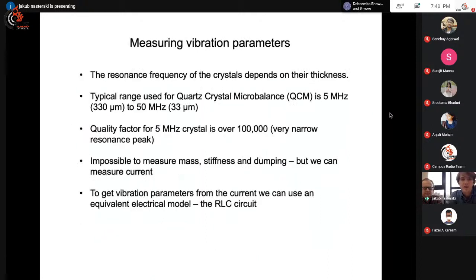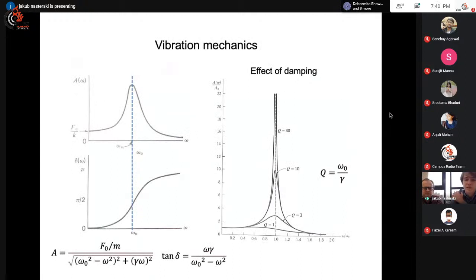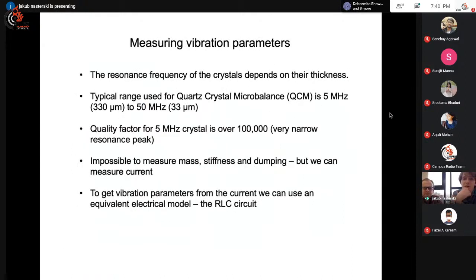But okay, so this is just the physical background. Now, because we want to measure it, let's just look at the numbers here. The typical natural frequencies of quartz crystals that we use for QCM, that's quartz crystal microbalance, is around 5 to 50 megahertz. So that's 50 million cycles per second.